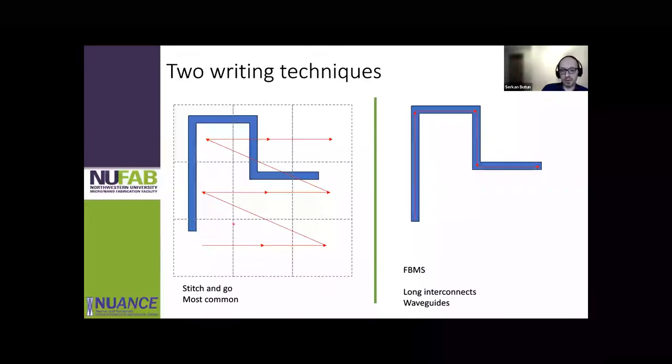For tips for new users: just start using PMMA. If you can't make something work with PMMA, odds are you can't make it with any advanced resist. If etching is your priority, you can make a liftoff process with PMMA and make a metal mask on your substrate to use in the RIE. The ZEP520A can be spun to about 100–150 nanometers with our composition and has higher sensitivity than PMMA, so develop times will be shorter.